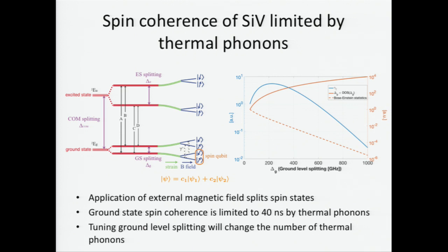And the physics involved there is this gamma term here. From within the ground state orbitals, from the bottom branch to the upper branch, it is very, very sensitive to lattice vibration. Whenever there is some vibration at the corresponding frequency, it can do a resonant absorption of the phonon, and then your orbital can jump from here to there. At that moment, its coherence gets destroyed. At a finite temperature, there are always thermal phonons. This fluctuation is stochastic, it's out of control. And that tends to happen every 40 nanoseconds. So that's why it only has 40 nanoseconds.